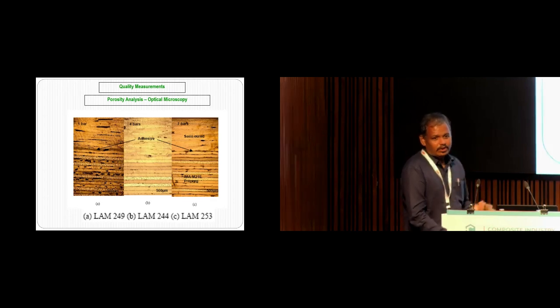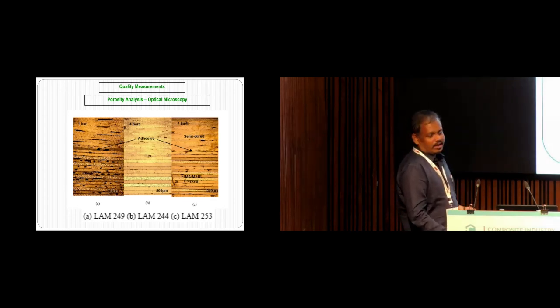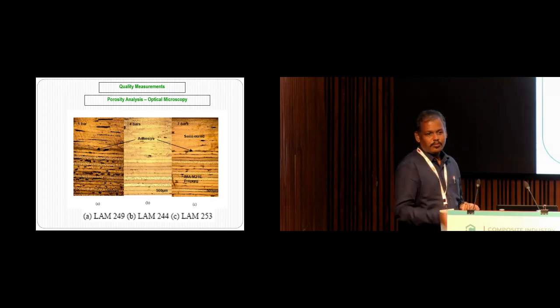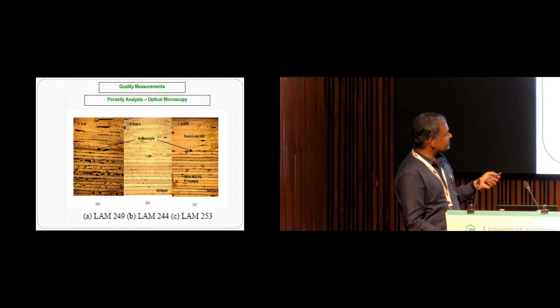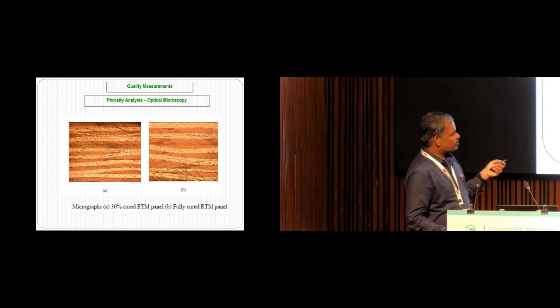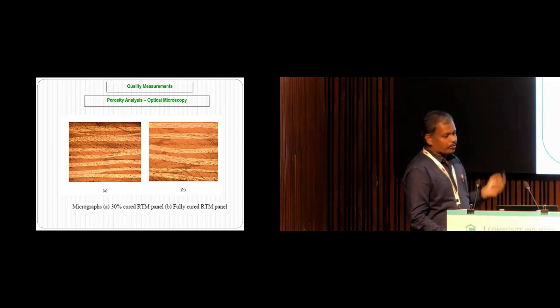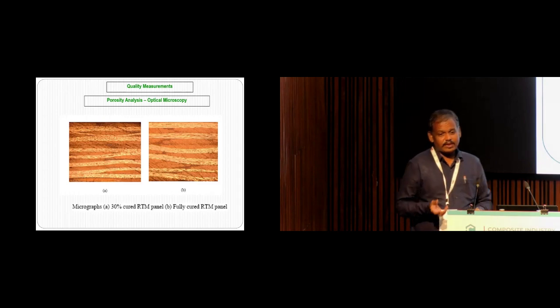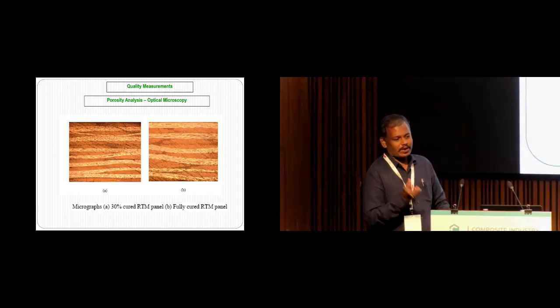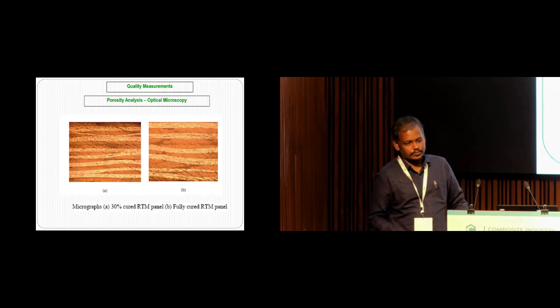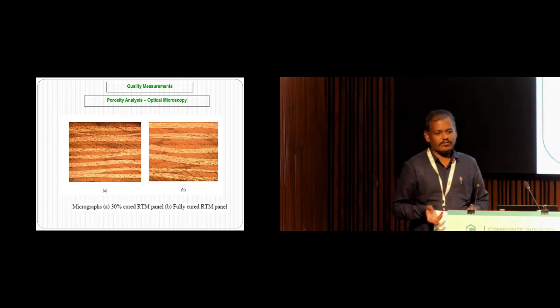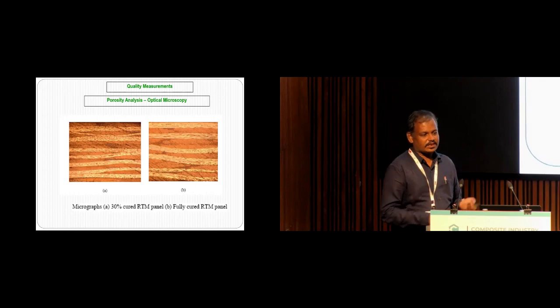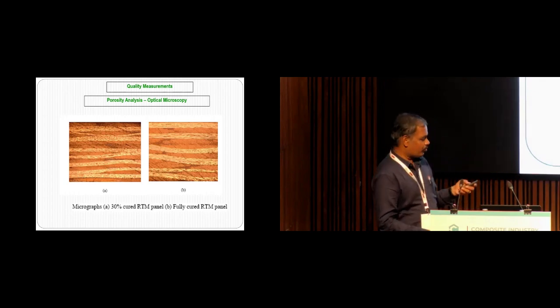This is simple optical microscopy. When you cannot afford high-end pore volume analysis, you can go for optical microscopy. If there are any macro pores, you can easily obtain them from optical microscopy. This is the composite, fully cured as well as semi-cured. There may be a change in the porous nature with respect to degree of cure also, so we tried to find out whether there is any pore volume change between semi-cured and fully cured panels.